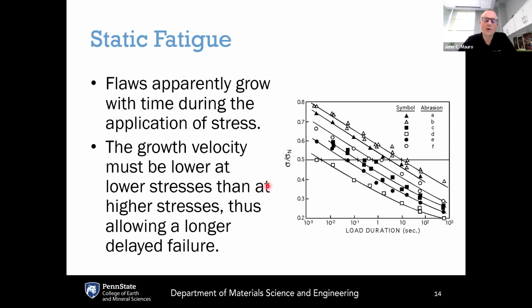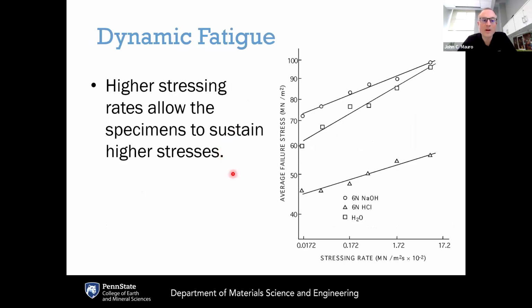If this is occurring where the glass is under some sort of constant stress or constant loading condition, this is what's called static fatigue, where the flaws grow over time due to application of stress. Over time, the strength of the material is compromised because of the reaction with water and the progressively lengthened crack. This can also occur as dynamic fatigue, which is based on how fast you apply load to the material. If you apply a faster load, you can observe a higher effective strength compared to applying the same load over a longer period of time, because a longer period gives more time for water molecules to react at the crack tip.